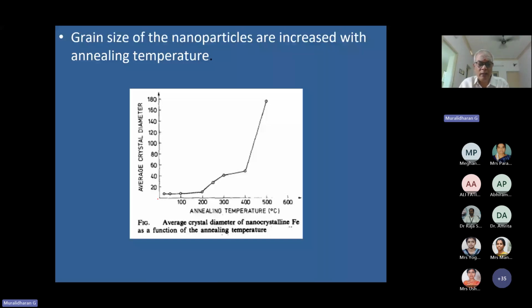You can see that the material, which was about 10 nanometer in size, at room temperature has become 40 nanometer at 300 degrees centigrade, and about 180 nanometer at 450 degrees centigrade. That means one has to be very careful in storing them at different temperatures. It's very essential that we understand this,